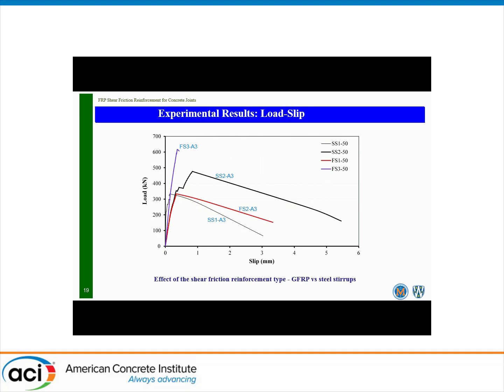Comparing the behavior with a steel reinforced one, we see specimen SS1 reinforced with just 1 steel stirrup, and specimen FS2 reinforced with 2 FRP stirrups. We can recognize that the ratio between the Young modulus, or rho times E, is still significant - steel here is still more than twice rho times E compared to the specimen reinforced with 2 FRP stirrups. Still, 2 FRP stirrups give a comparable ultimate strength and comparable stiffness to the single reinforced steel specimen with just one steel stirrup, and both of them, after crack initiation, were weak - the reinforcement content was not enough to carry the load, and they failed suddenly.